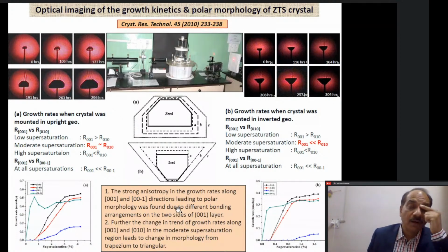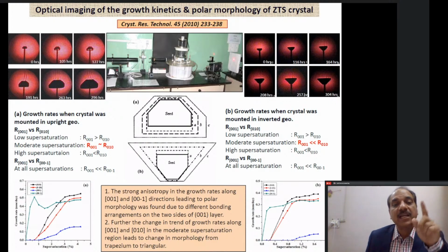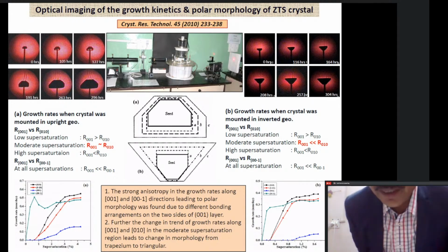So we found out what the bonding arrangement was in a 001 slice of ZTS, and we were able to show that there are certain bonds which are present only on the 001 side, but they are not present on the 00-1 side. And those dangling bonds are the reason that most of the growth units are coming and attaching to that surface, and nothing is going on the other surface, because of which the crystal was growing more in one direction and less in the other direction. Excuse me, I'll just take some water.